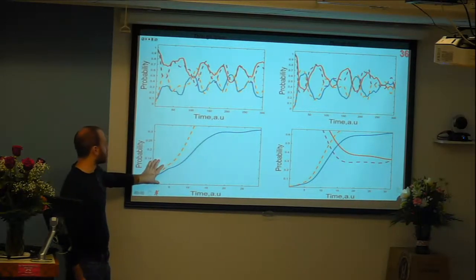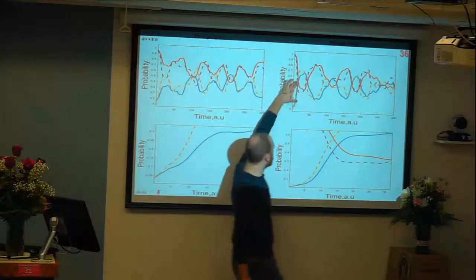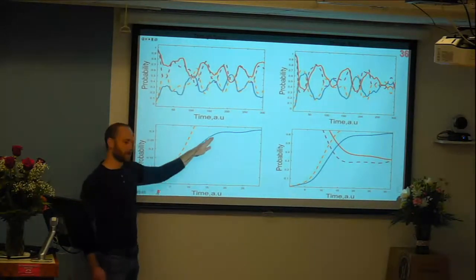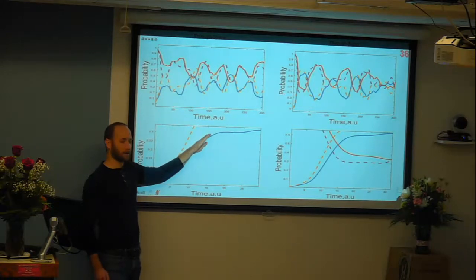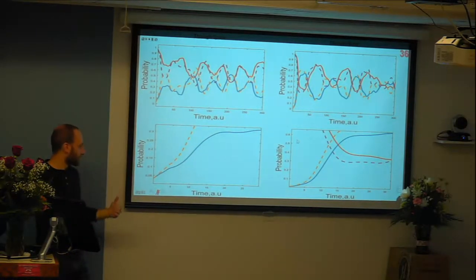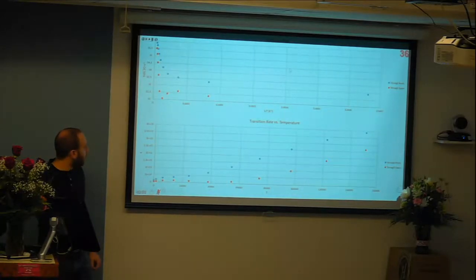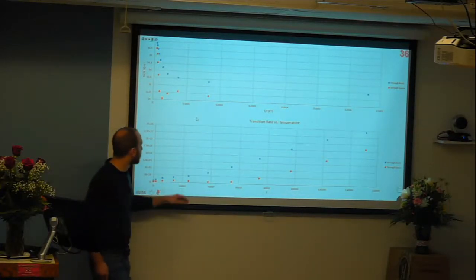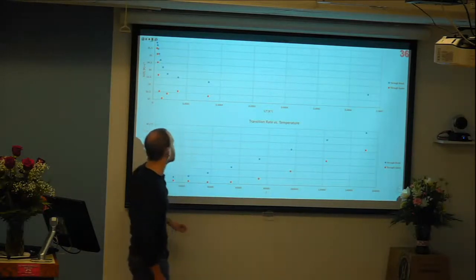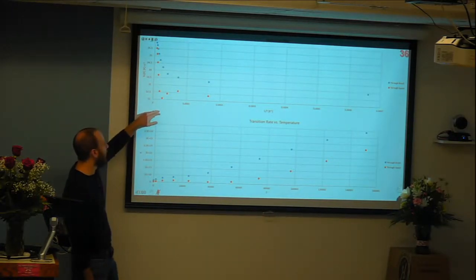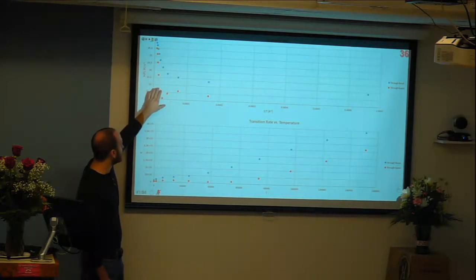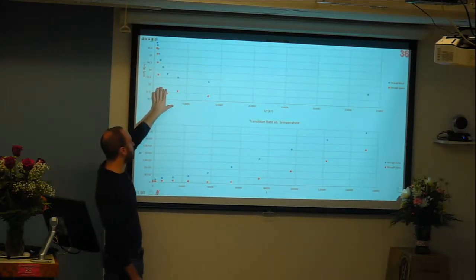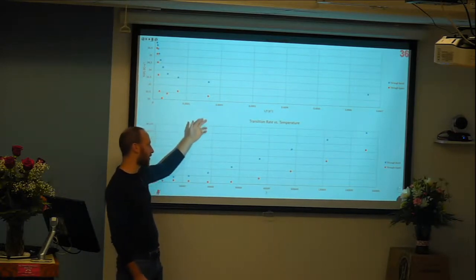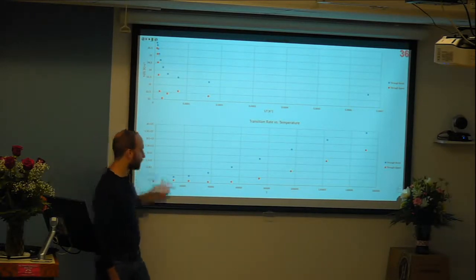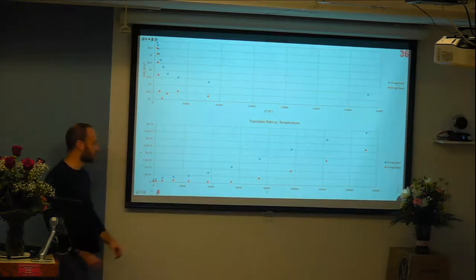So you zoom into these graphs, look at this section here and this section here, and figure out the slope of this linear region to determine the rate at which the electron is transferring into the perovskite. And you end up getting these transfer rates which have unphysical temperatures, but you get a very interesting phenomenon where the Arrhenius plot certainly doesn't obey the Arrhenius equation, because if it did, the Arrhenius plot would appear to be linear. Instead, it appears that the transfer rate is directly proportional to the temperature of the system.